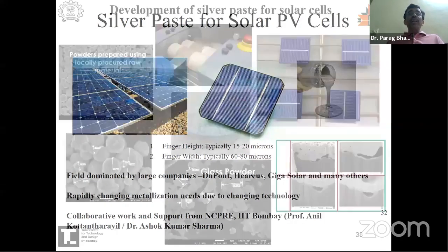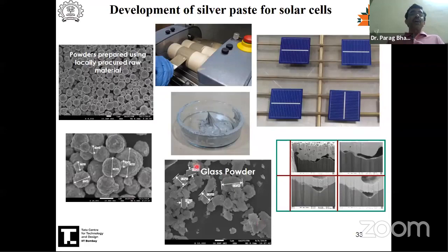Now, what we do in our lab is, this is the interesting part from materials or metallurgy viewpoint. If you see, that white bar is 1 micrometer. So we make all these silver powders in our lab. Okay, you can see the zoomed in picture. This is another picture of paste. So these pastes have silver powder. These pastes have a special glass powder. Then we add some organics, and then we do high shear mixing by what is called a 3-roll mill.